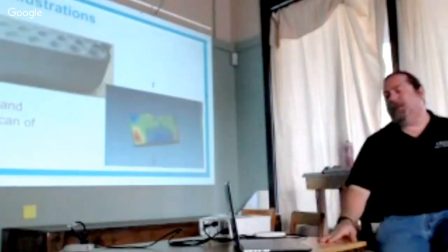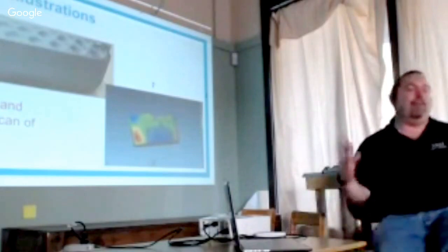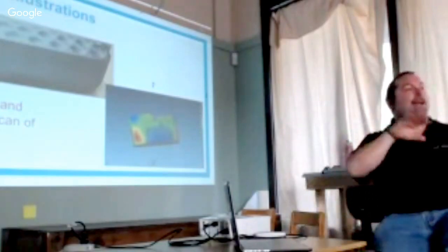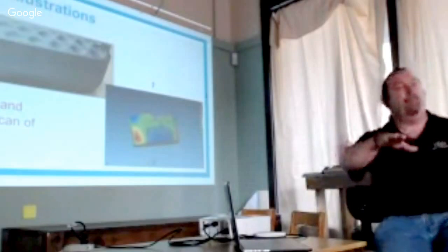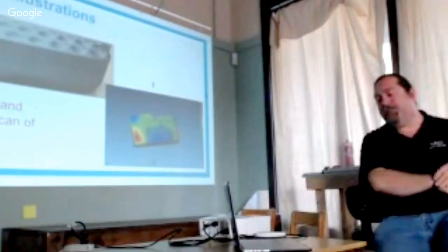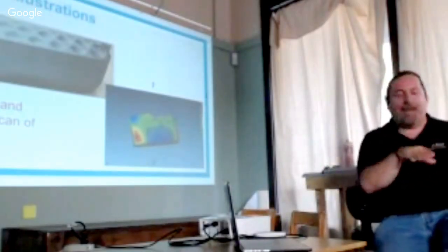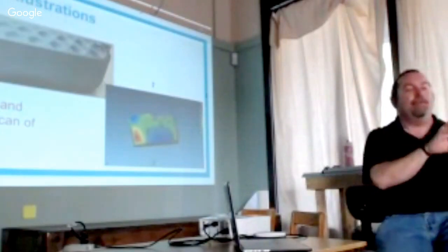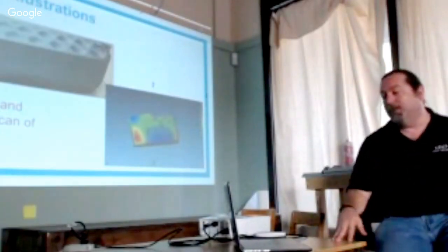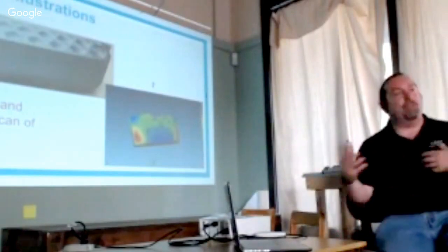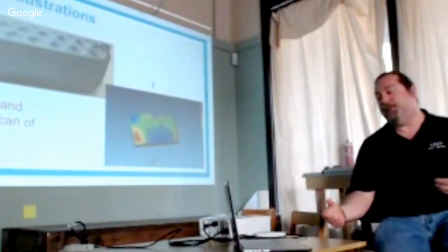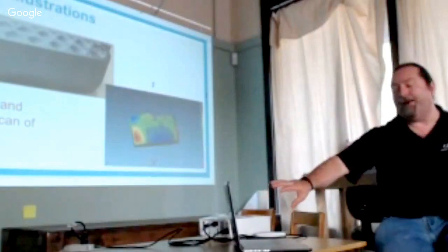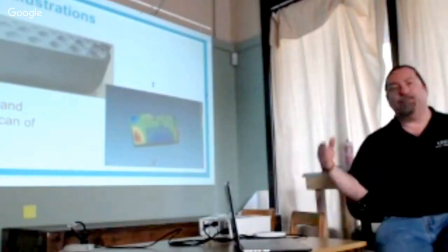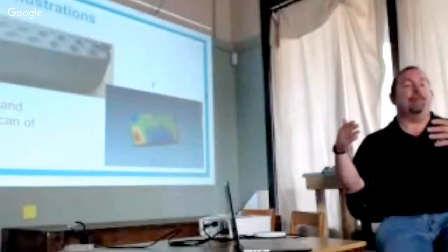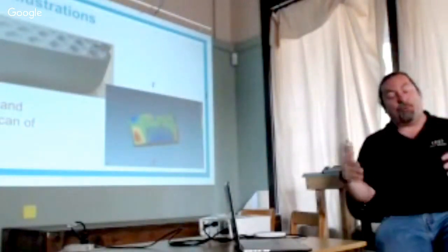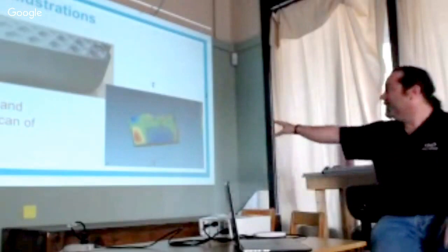So then we came up with this tool test print. We had a design of a windshield mold to thermoform a windshield, half of that, and then we added some features to give us a variety of typical features for a tool. With each new material, we started printing this test print, and then we would scan it after it was printed. Then we could show the deviation of the print from the original design, and that's what this shows.